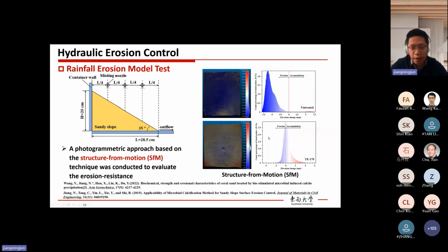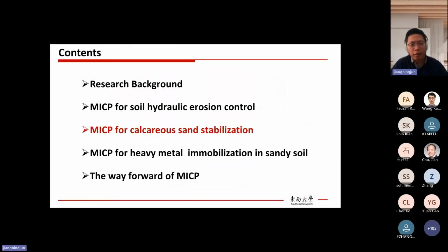For the MICP treated sample, it's quite different. We almost see no erosion, only a little bit on the lower part, and we could also see some accumulation on the toe of the slope. So this research also demonstrates the effectiveness of MICP in preventing surface erosion of sandy slopes from rainfall. Okay, so that's the first part.